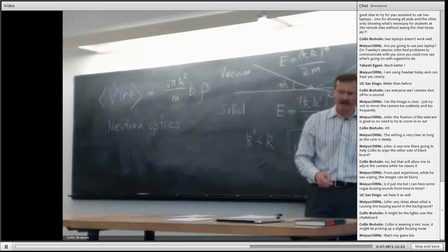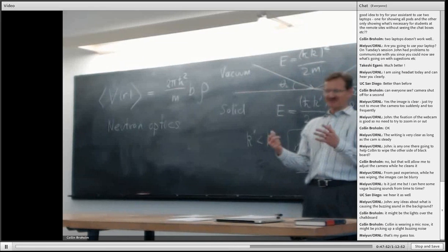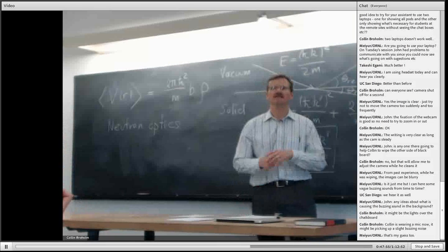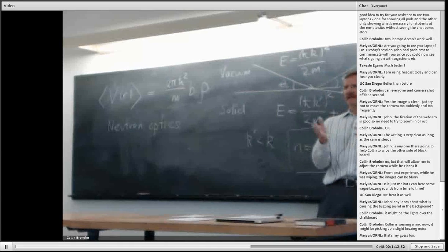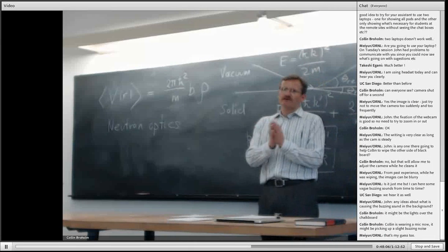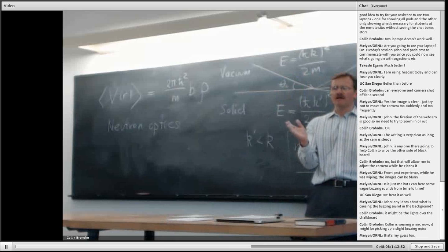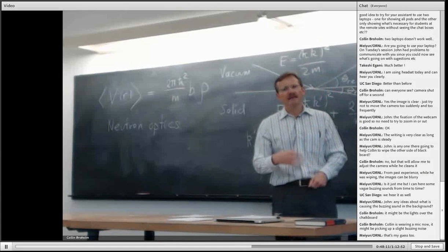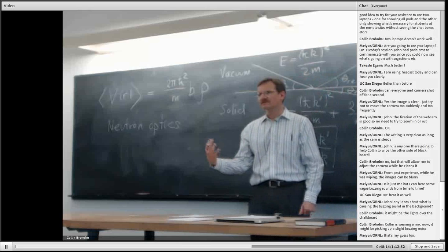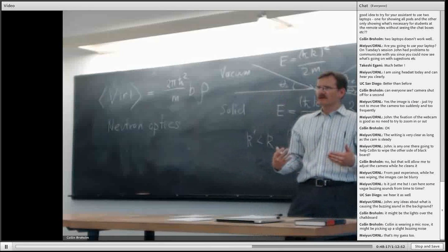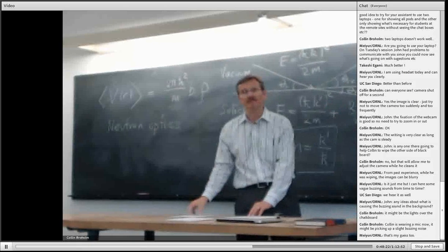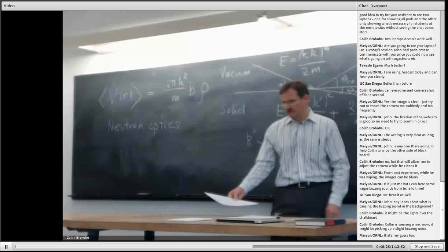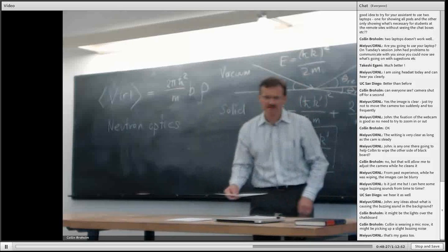Some nuclei do have a big appetite for neutrons, if we may say it like that. For example, boron-10 would just love to become boron-11, which is a predominant isotope. And so it has a large absorption cross-section. Cadmium is another example. Gadolinium is another example. So these are materials that are hard for us to do neutron scattering experiments on unless we isotopically purify them. On the other hand, we can use those materials to absorb neutrons. So we can use them when we want to absorb the beam. If we want to shape the beam of neutrons, then we would use perhaps boron, perhaps cadmium. And we could say a few words about this process.